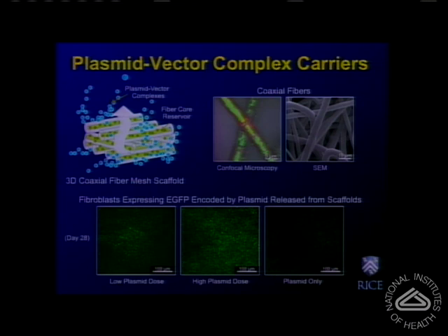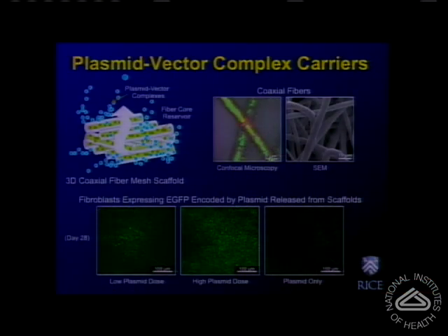One such technique is from our laboratory, reported recently in the literature, that involves the use of coaxially electrospun fibers that can be used as a scaffold for the culture of cells, but also for the controlled release of these complexes. And the innovation in this particular system is that one can load separately the polycationic polymer within the shell of the fiber using coaxial electrospinning, and also load the plasmid within the core of the fiber. So one can use a very hydrophobic polymer as a shell for the fiber and a very hydrophilic polymer as a core. One can load and deliver separately both the plasmid and the polycationic polymer, and as these components are released to the surrounding medium, they complex, they form a polyplex, and this polyplex that is formed following their delivery can transfect surrounding cells.